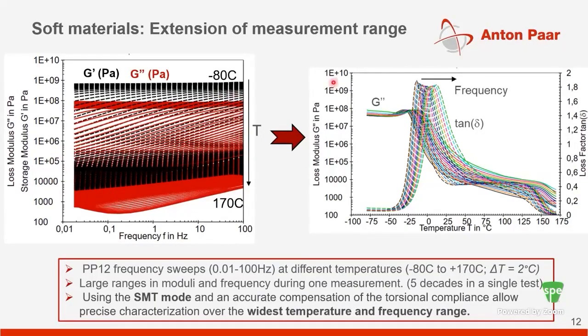This is data generated on an SMT type device, showing frequency sweeps done at a bunch of different temperatures from -80 to 170°C in 2 degree centigrade intervals. You can see there's a bunch of different data here, and characterization across the entire frequency space of the rheometer, which typically has specs of 100 hertz—you can see how you can characterize the materials completely up to 100 hertz.